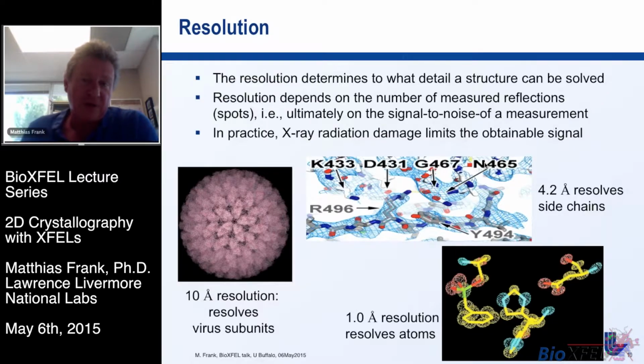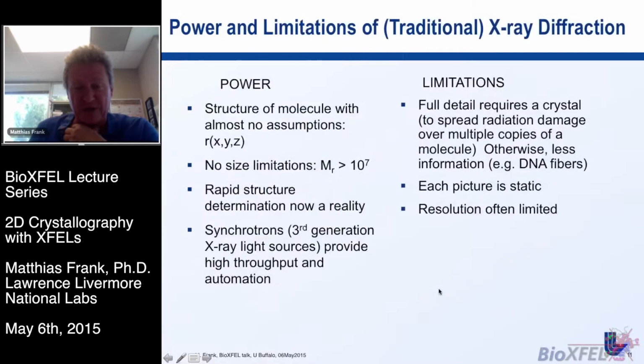Resolution really determines to what detail a structure can be resolved, and it depends really on the signal to noise of your measurement and the number of measured reflections. In practice, X-ray radiation damage limits the obtainable signal. So just to give some examples, if you have a resolution of 10 angstrom, you can resolve viral subunits. If you have about 4 angstrom resolution, you see some residues on amino acids in proteins. And if you get all the way to an angstrom and a half, you actually resolve individual atoms.